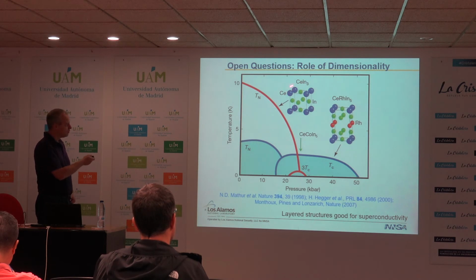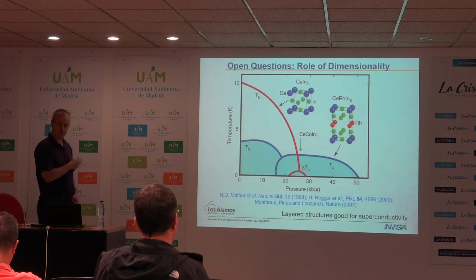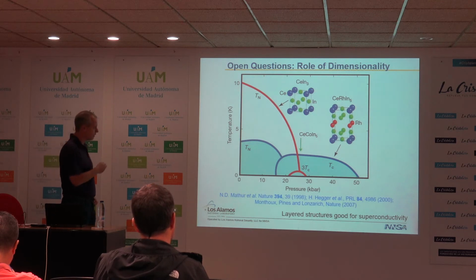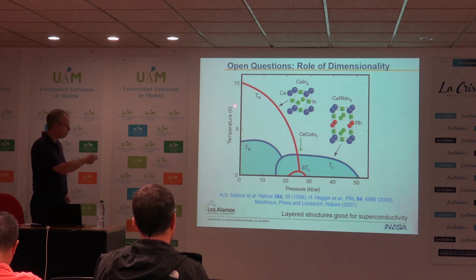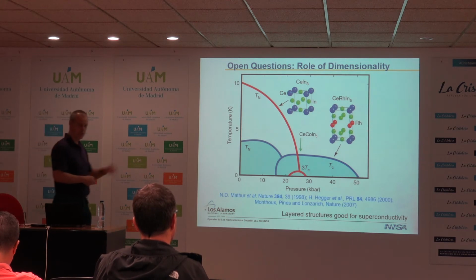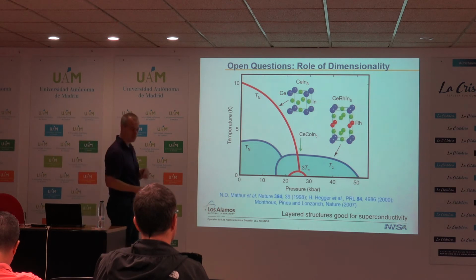So cerium indium 3 is a cubic system. It's an antiferromagnet. It orders magnetically at around 10 Kelvin. And here you see temperature as a function of pressure. The work by the Cambridge group initially showed that the antiferromagnetism comes down and you have this beautiful dome of superconductivity. Maximum TC of this dome is 0.2 Kelvin.